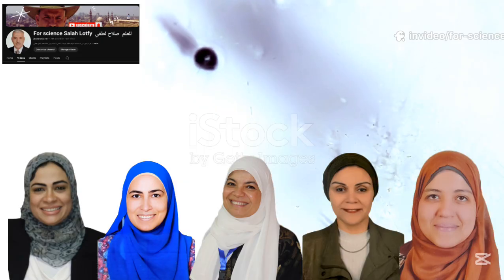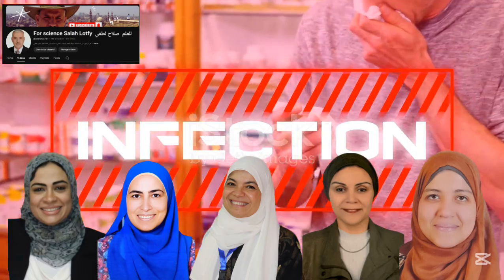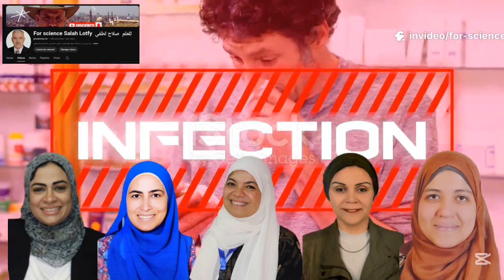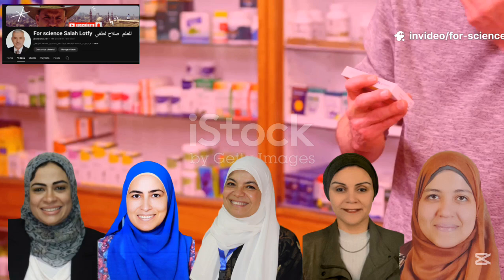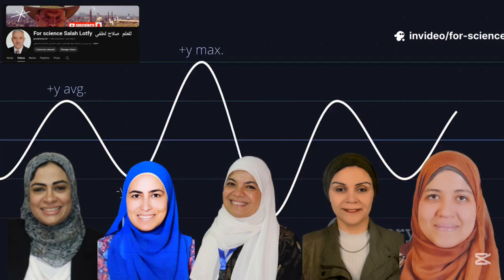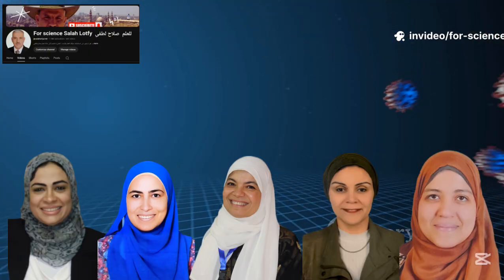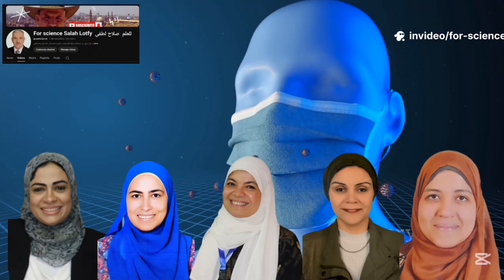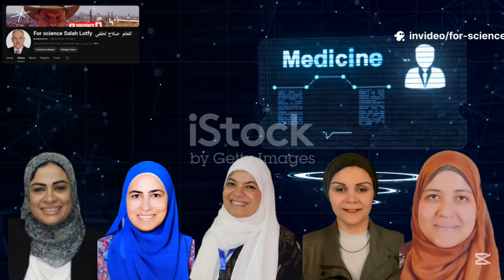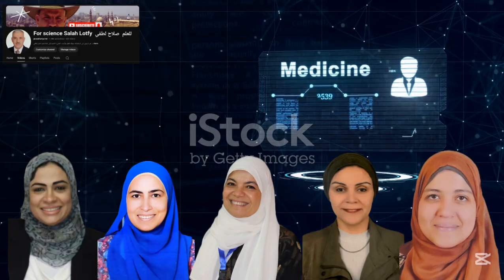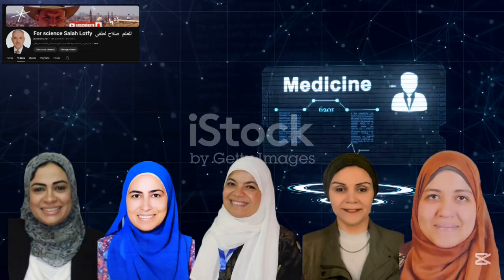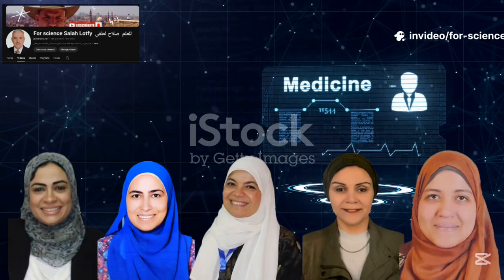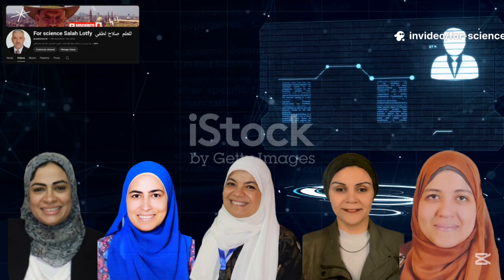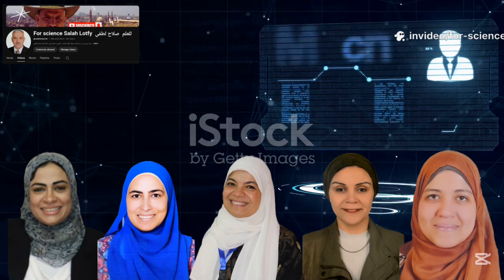Biofilm formation is a major obstacle in chronic wound healing. The 5% LVO Ag-ZnO hydrogel inhibited biofilm formation significantly, up to 69.5% inhibition for Bacillus subtilis, between 56% and 65% for other strains including S. aureus and C. albicans. Lavender oil disrupts bacterial membranes, while Ag-ZnO prevents adhesion, stopping biofilm development at its early stages. Together, these results prove that LVO, PVA-pectin, Ag-ZnO nanocomposite hydrogel dressings combine the mechanical strength of synthetic polymers, the hydrophilicity of pectin, the antimicrobial action of silver-doped ZnO, and the healing boost of lavender oil.